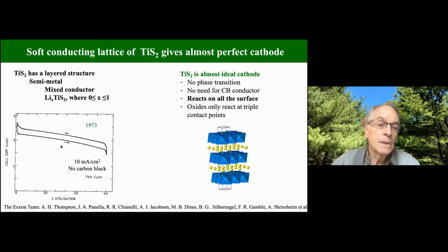So if you look at titanium disulfide, it's what I would call a metallic conductor. So you don't need to put any carbon black in it. And this gives it the advantage that the reaction occurs on all the surfaces of the titanium disulfide, not just where the carbon black, the titanium disulfide, and the electrolyte meet. So inherently, it's got a higher rate. And being a metallic conductor, the electrostatic repulsions from the lithium ions are minimized.